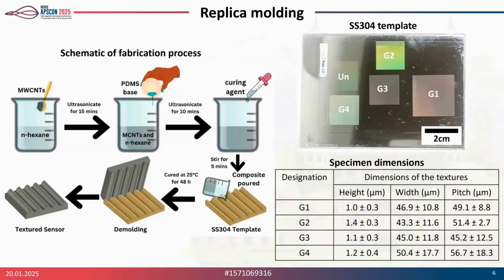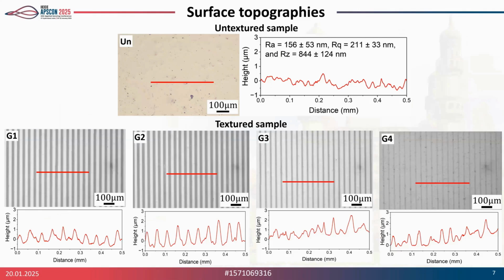So four such textured samples were prepared with the dimensions given here, and one untextured sample was prepared for reference. And as you can see, the optical micrographs and line scans of the prepared sensors. In the optical micrographs, you can clearly see the surface topographies are well replicated from the laser template. And in the line scan, you can see the topographies of the prepared samples.